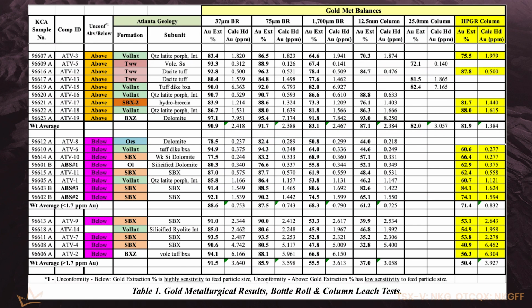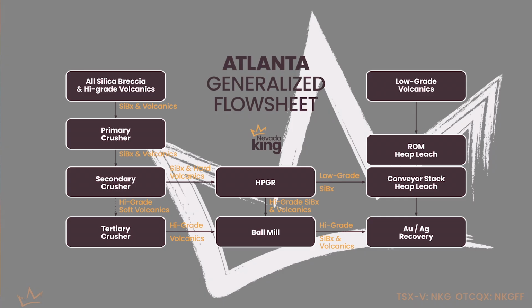Confirmed our anticipation that the volcanics acted more like conventional heap leach materials across central Nevada, Carlin-style materials, where they achieved reasonably high recoveries, 70s and 80s in the laboratory on conventional crushed materials, and projecting those to run of mine. The run of mine recoveries are very good, and the volcanics appear to be very amenable to low-grade run of mine heap leaching. The higher grade recovery increases by about 10-15% depending on the grade, and that material would be suitable for milling. So we ended up with a scenario out of phase one where milling the high-grade volcanics and run-of-mine heap leaching the low-grade volcanics will probably be a suitable route for processing those material types.